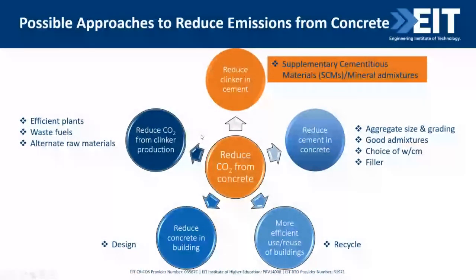Studies have revealed that people can reduce emissions by about 80% with known technologies if we make the most of the approaches listed here. First, we can look at reducing carbon dioxide from clinker production. There has been a tremendous achievement in the efficiency of cement plants over recent years, and the production process is highly optimized to about 80% of the thermodynamic limit. Of course, there is possibly still some room to improve, but not very much, and it is also very difficult.